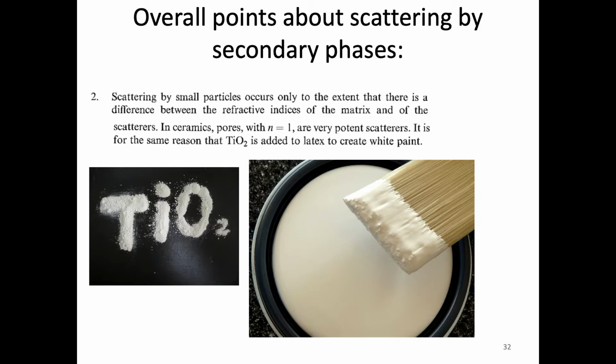And so that takes something that should inherently be clear, so light just passes through it. But if we have that material as a small particle or with lots of pores and defects, something like TiO2, again, should be clear, but because of that, it becomes a very strong scatterer. And when we scatter light, that makes it white. So TiO2 is used very much in the paint industry to make things white because it scatters light.